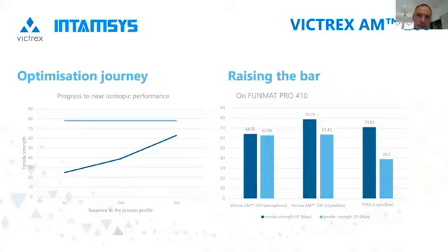And the bar chart that you can see on the right-hand side shows some data from printing AM200, firstly amorphous, which is the first two bars on the left of the graph, where there's a fairly good XY, but especially the Z properties are achievable up there at 62. And these may be enough for many applications. Amorphous can give precision parts and more ductile material, and as you can see, is still pretty strong.